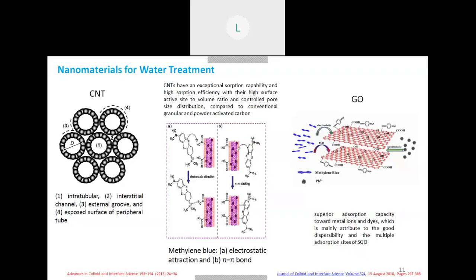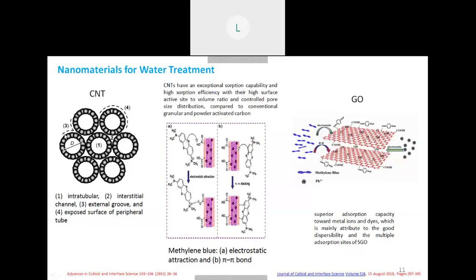But if you go through the literature, you will find the CNTs are better materials than the activated carbons, because they have huge surface active sites. One is the intratubular, the second is the interstitial, the third is the external groove, and the fourth is the outer surface area, which is the periphery of the material. But you will find this pore size is very small, like 0.3 nanometers, so no pollutant can be adsorbed in this area.